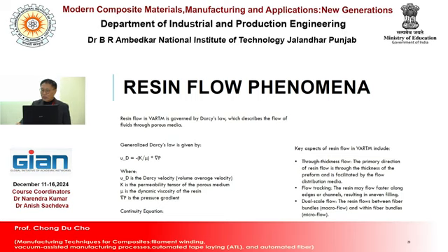The through-thickness flow means the primary direction of resin flow is through the thickness of the preform, facilitated by the flow distribution medium. You can see that later. Flow tracking means the resin may flow faster along an edge or channel, resulting in uneven filling. And dual-scale flow means the resin flow occurs between fiber bundles and within fiber bundles. Between fiber bundles is macro flow, and within fiber bundles is microflow.